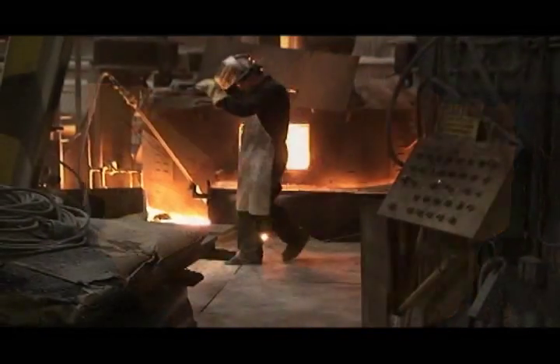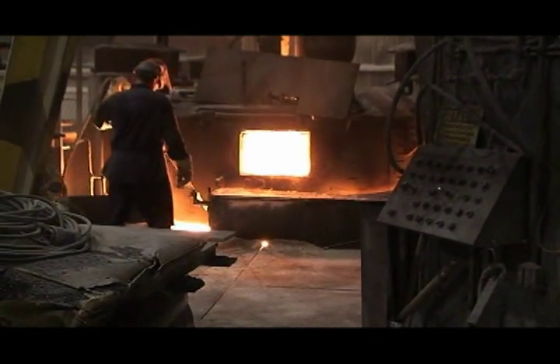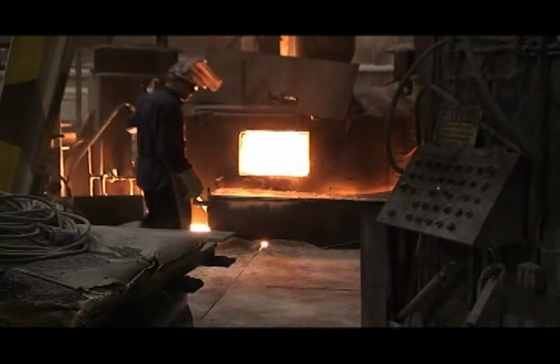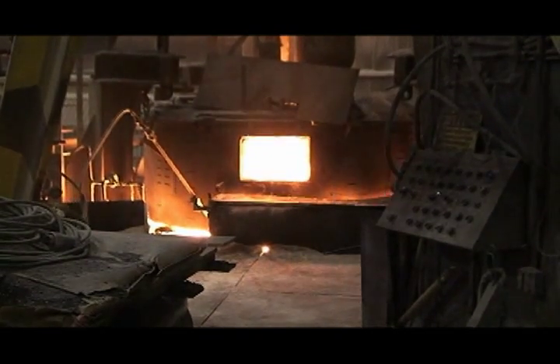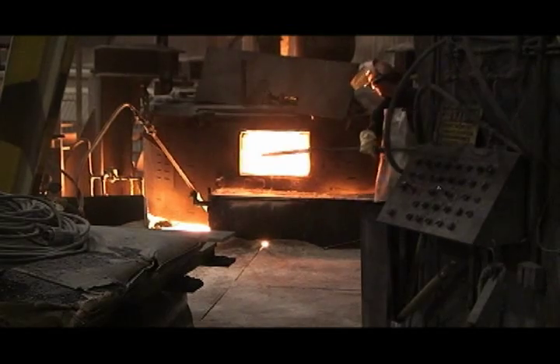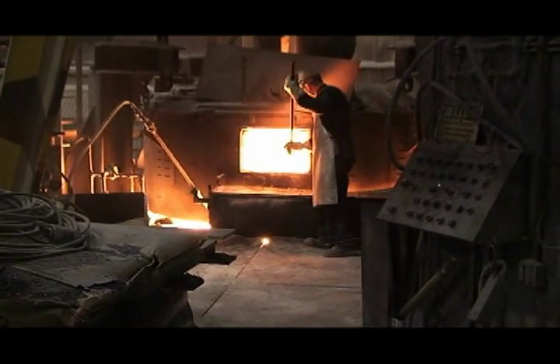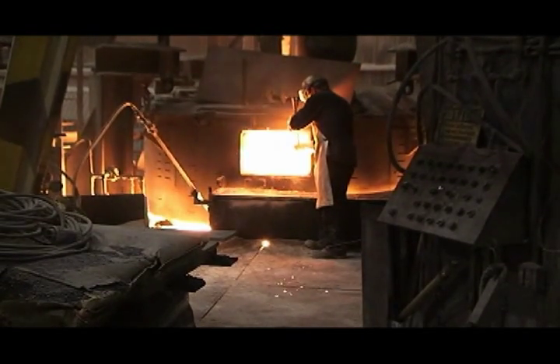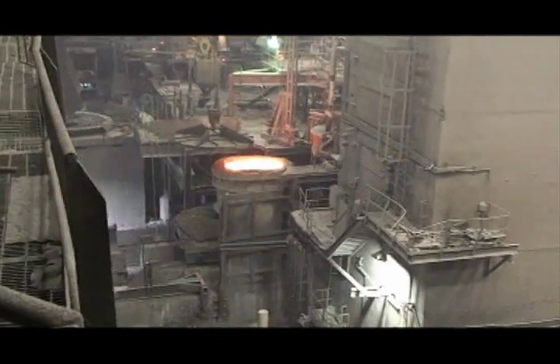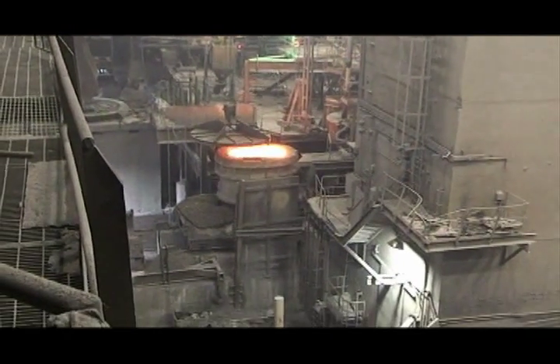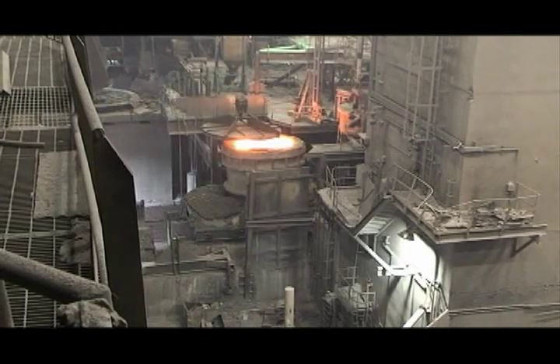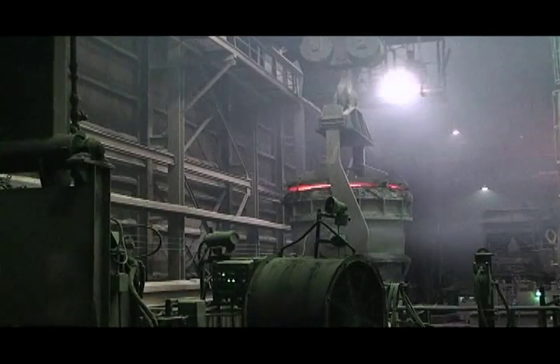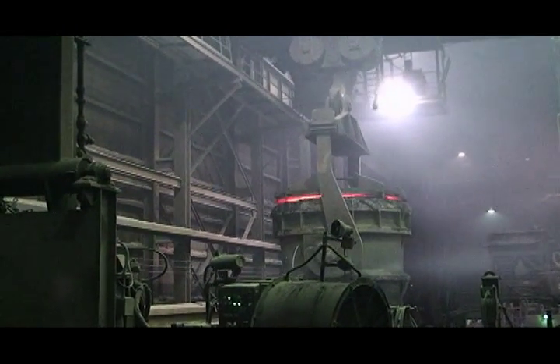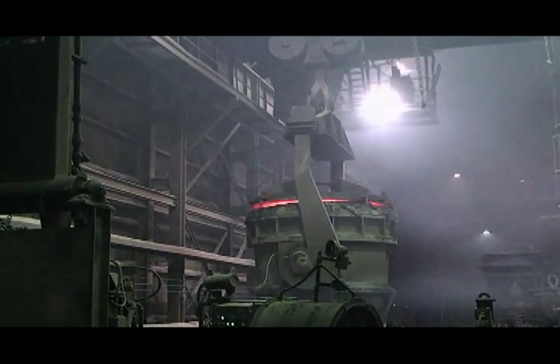At the ladle metallurgical furnace, alloys and fluxes are added to the heat to produce the desired grade of steel. To maintain quality control, the operator takes samples from the ladle of molten steel and sends it to the laboratory for analysis. The ladle leaves the furnace by a remote-controlled car. The hot metal crane puts a lid on the ladle to preserve the temperature of the steel while transporting it to the casting machine.